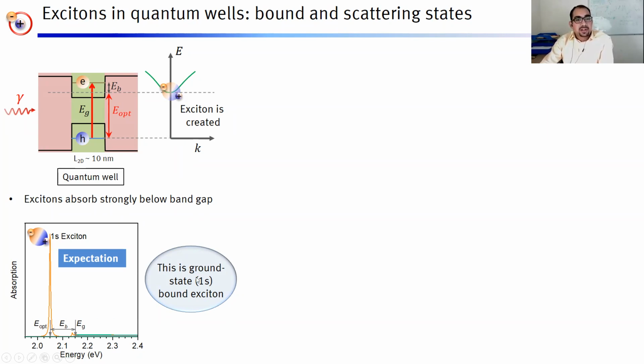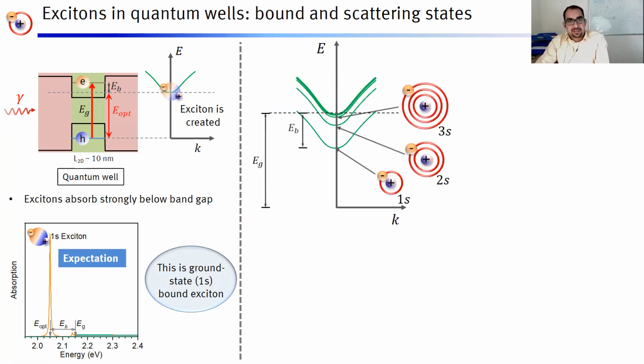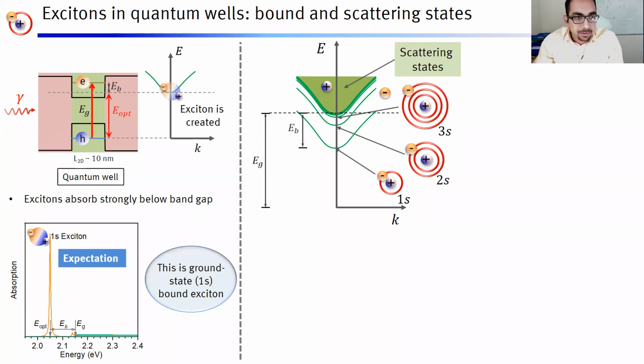So this is a ground state of exciton, ground state of bound exciton, because just like in the hydrogen atom, there are ground states and excited states. That is shown here. So an exciton itself has its own parabolic E-k diagram. So you have a ground state, 1s state, which is expected here. But then you also expect these 2s, 3s, and so on, these excited states. Additionally, you also expect scattering states or unbound states of excitons as well, which start from the band edge, meaning where the binding of the states stops. That's the single particle band gap. So there you should start seeing some contribution due to the scattering states of excitons.